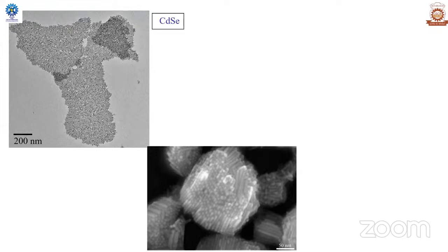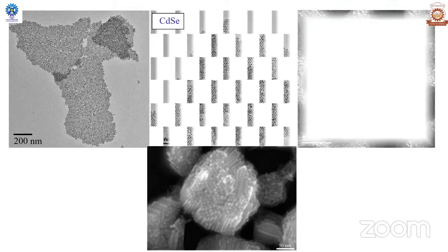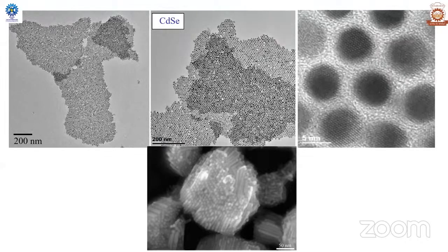Okay, so these are some of the structures which were synthesized in the labs. And you have the cadmium selenide, then the cadmium sulfide, and various types of nanorods. So eventually, they have been assembled over large areas. The top picture shows they have been synthesized in the organic medium, whereas the bottom picture shows that they have been transferred into the aqueous medium also, and there has been phase transfer by use of different pluronic surfactants and block copolymers, and this ensemble of these nanorods has been generated. So these are different synthetic strategies.